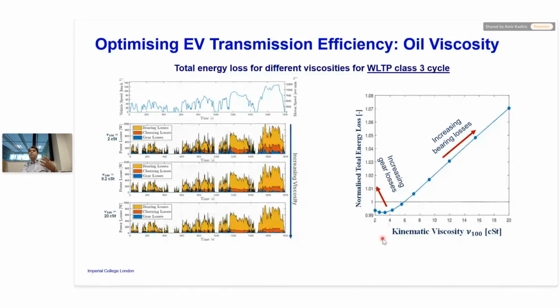There is an optimum viscosity, which is relatively low for this particular cycle and this particular gearbox, but it isn't 0, it isn't 1 centistoke, it isn't 2 centistokes. There is an optimum that we can predict. However, this is specific to the gearbox, specific to the cycle.